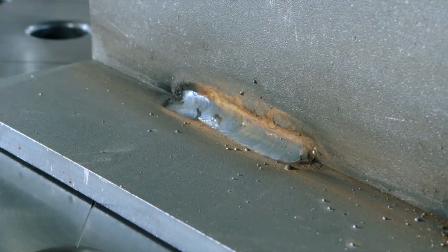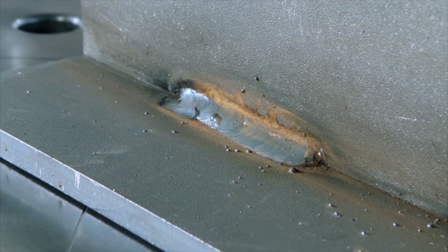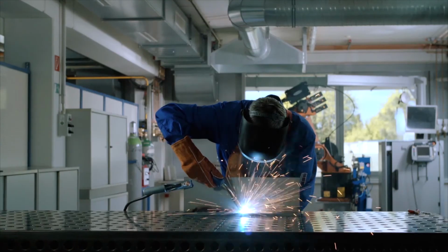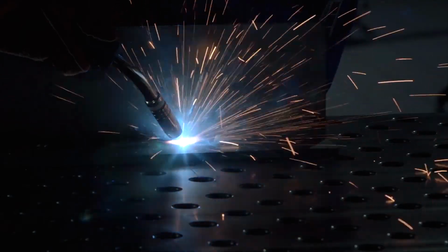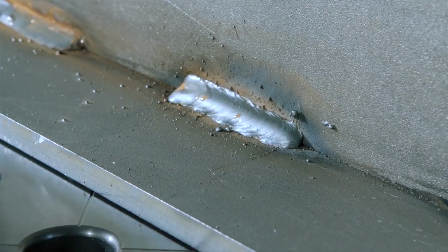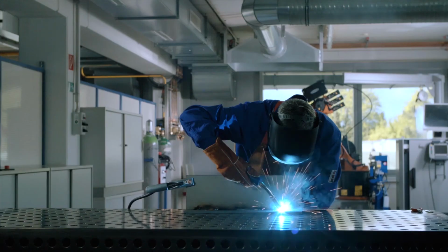In this case, you can see that the weld seam is concave. This is because the wire feed speed is too slow. If the weld seam is convex, the wire feed speed is too high. A good weld seam looks like this.